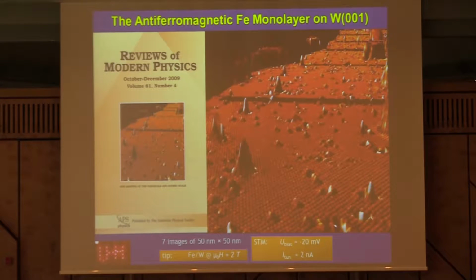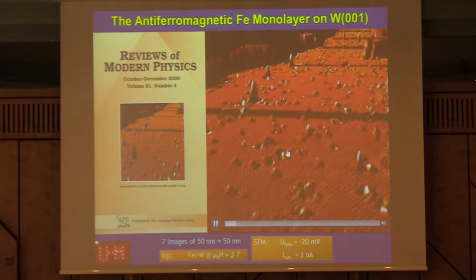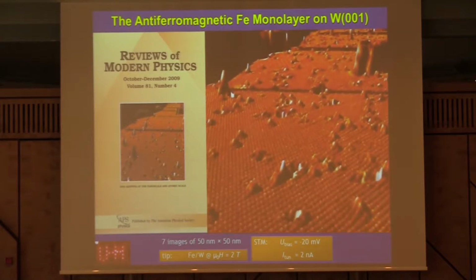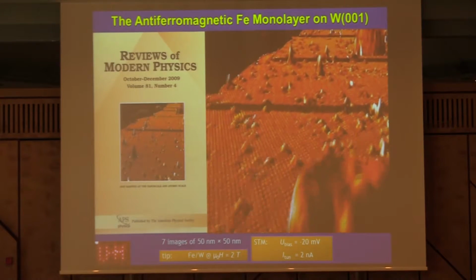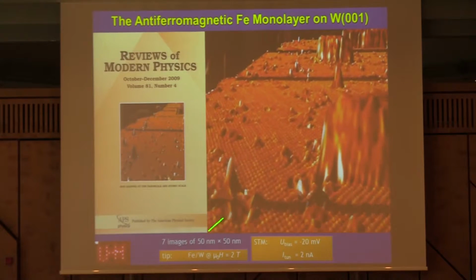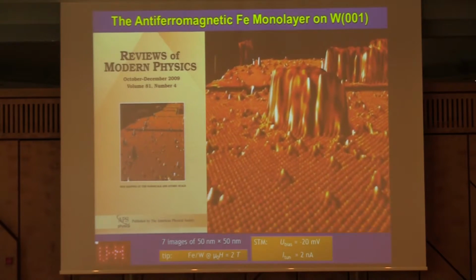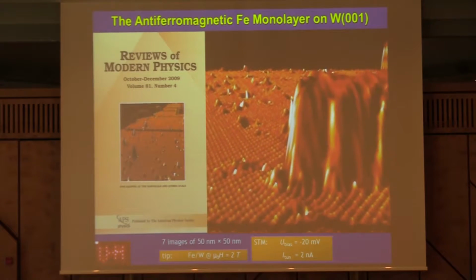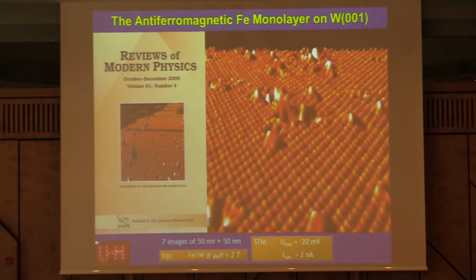But nevertheless, we scanned over several tenths of micrometers by putting together a large number of atomic resolution images, and we could see the beautiful coherence in the spin lattice here over mesoscopic distances. So there was no domain boundary here, which we were actually looking for at that time. We saw basically a perfectly coherent spin lattice in this case.